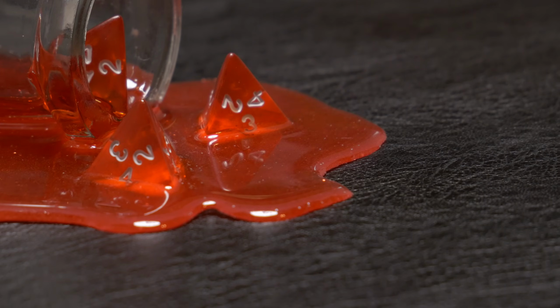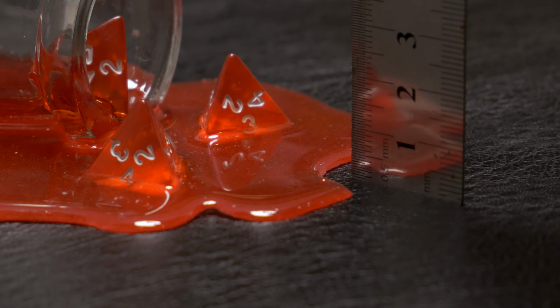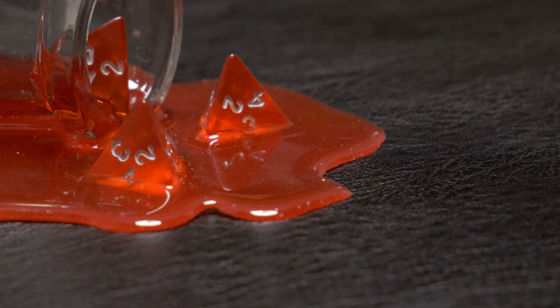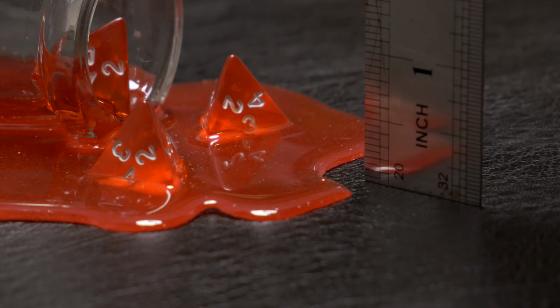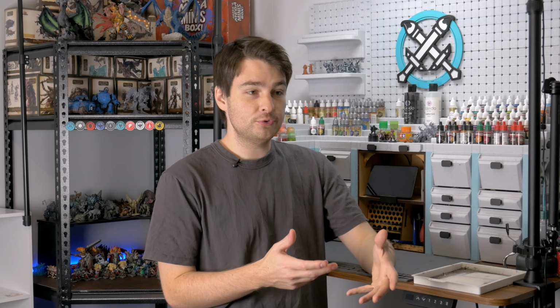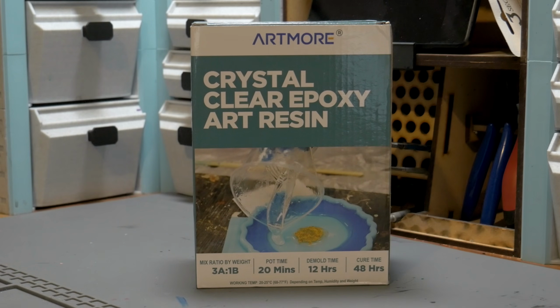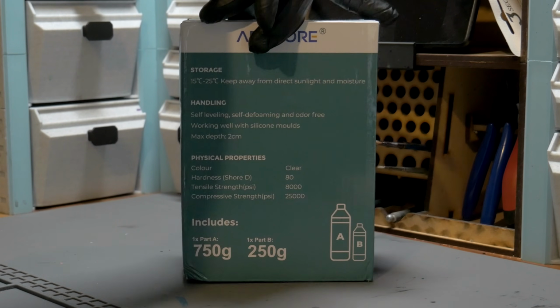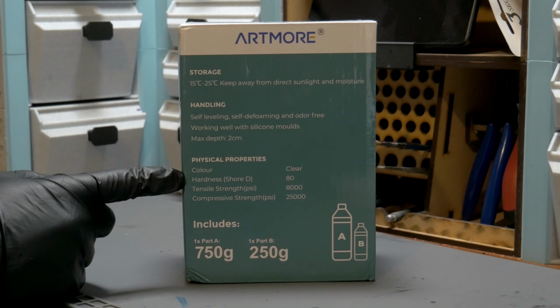But as I suspected, it also could have been the depth of the potion spill wasn't actually enough to cure fully, so those are two things that I need to be careful of. Secondly, I learned that there are, unsurprisingly, different kinds of resin, and with different hardnesses within those types. Some resins are designed to remain flexible, to be used more as a coating over other art mediums, while some resins are designed to cure fully hard. Moving forward, I went ahead and picked up a proper art resin, with a hardness rating of 80, which is the sweet spot for things like dice.